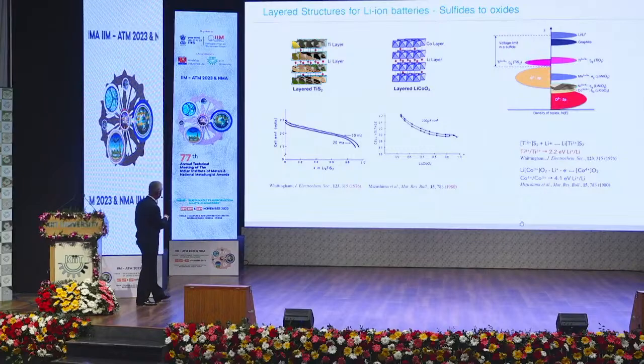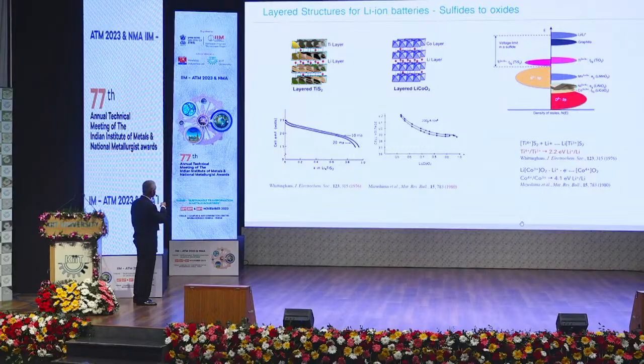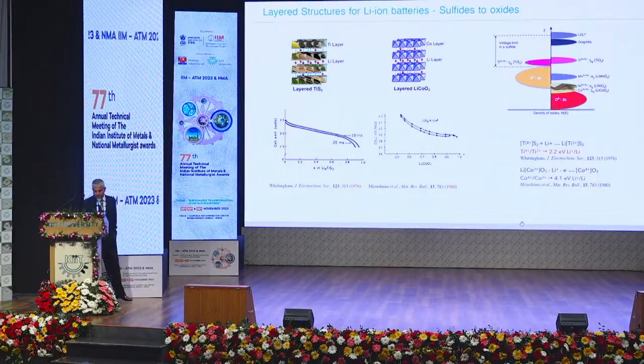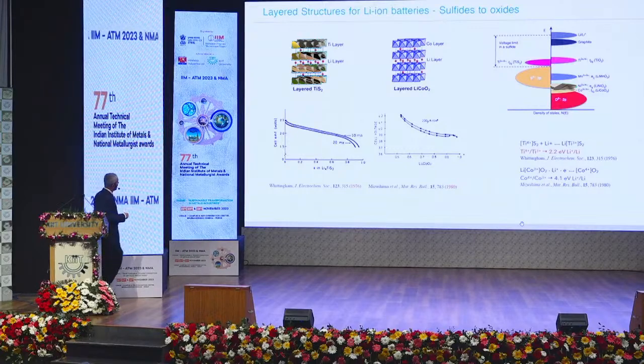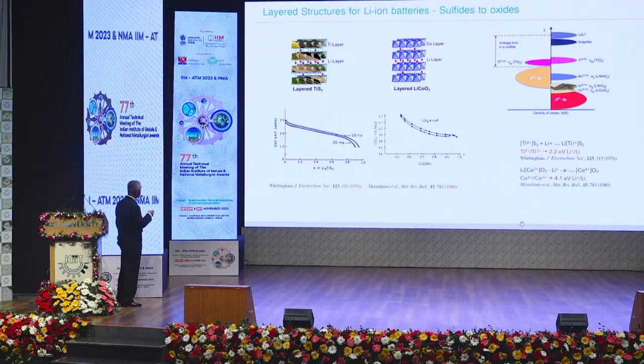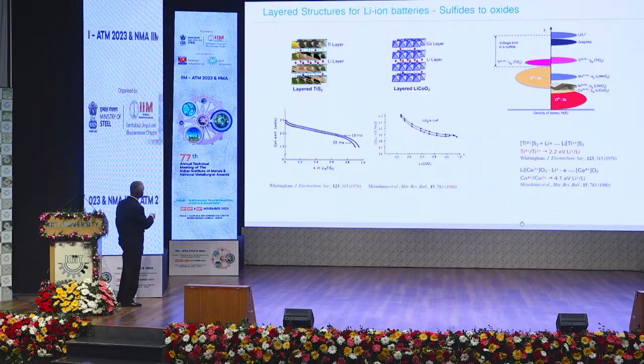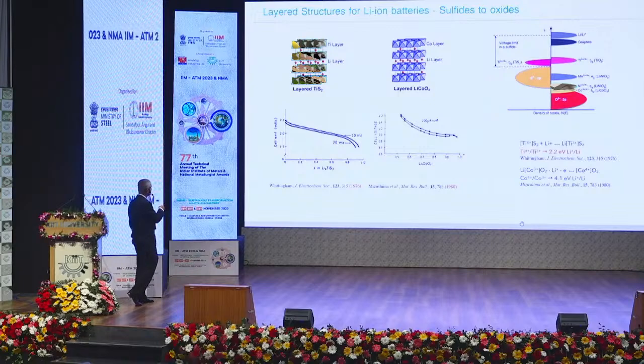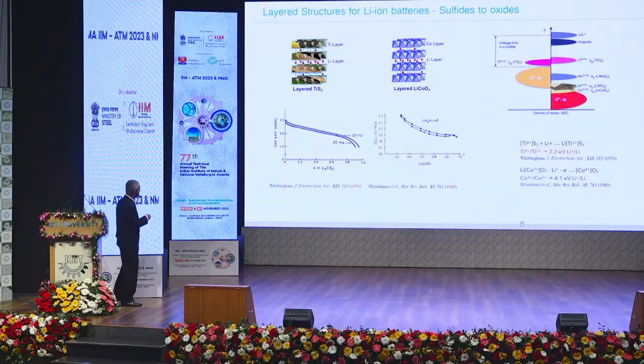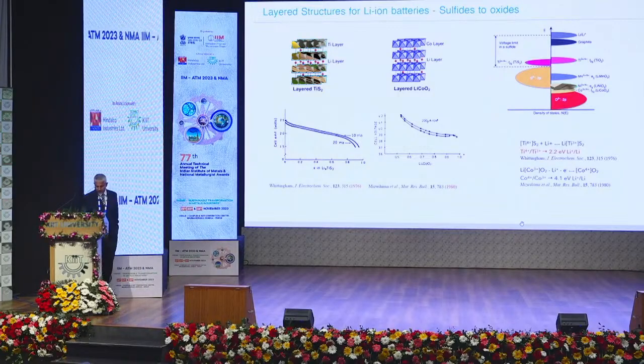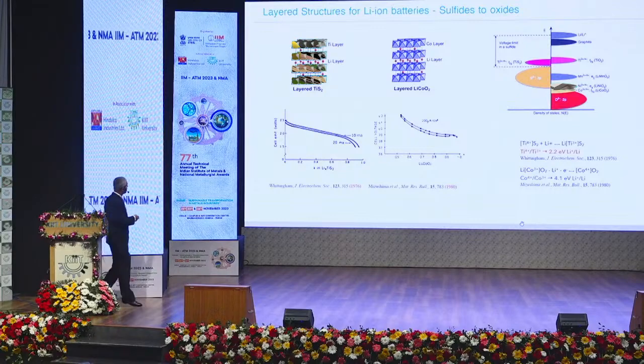Dr. Whittingham was working as a scientist, and he showed that you could electrochemically insert lithium into the layers of titanium disulfide. And he created this concept of the lithium-ion battery that was very important. When we insert the lithium into the titanium disulfide, the titanium 4+ will be reduced to titanium 3+ at 2.2 volts.